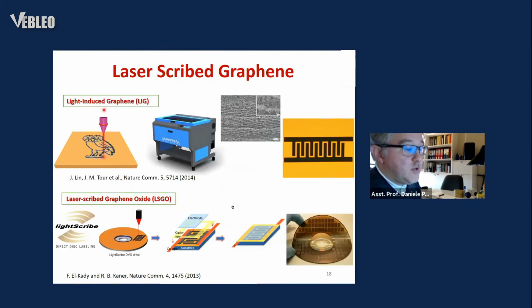And in our lab, we are developing a novel method to produce graphene based on the laser photochemical conversion of a suitable precursor. It has been demonstrated, in fact, that it's possible to convert several plastics, such as polyimide, into graphene using an infrared CO2 laser, or even convert graphite oxide into graphene exploiting a cost-effective laser of a DVD writer. In both cases, interdigitated graphene electrode devices can be easily realized in a scalable way and very quickly for a wide spread of applications ranging from sensing to energy storage.